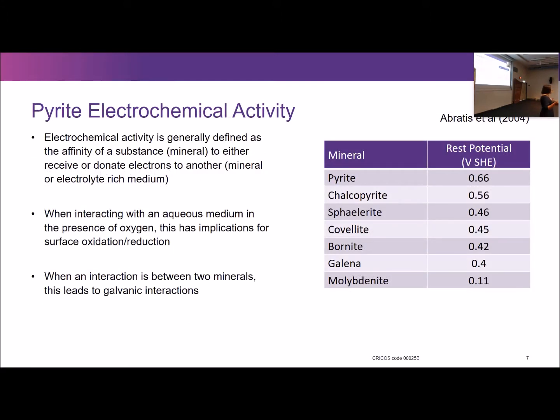So, what is pyrite electroactivity? What does that mean? Well, electrochemical activity is defined as an affinity of a substance, in this case a mineral, to either receive or donate an electron to another substance, another mineral, or an electrolyte-rich medium, a flotation or grinding medium, for example. So, when interacting with an aqueous medium in the presence of oxygen, this means that mineral surfaces tend to oxidize. When there is interaction between two minerals, it leads to a galvanic interaction. This is a table from Abraitis, which gives you the rest potentials, which are indicative of electrochemical activity of a number of really common base metal sulfides that we deal with pretty much every day in mineral processing, and pyrite sits right at the top. It is one of the most electrochemically active minerals that we deal with in base metals altogether.